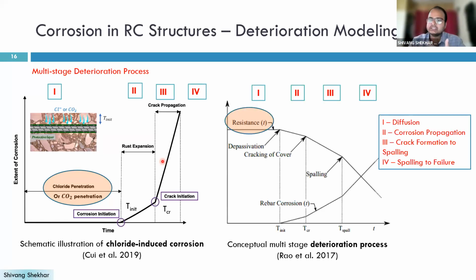In terms of resistance, you can see it here. Resistance is 100%, and once the corrosion starts, it starts to degrade, with cracking of concrete, then spalling of concrete. So basically we have 3 time instants: T initiation, the time to initiation of the corrosion; T critical, the time of cracking; and then the time of spalling of concrete. Your 4-stage multi-stage deterioration process is defined as diffusion of chloride or CO2 in the concrete, then corrosion propagation, crack formation, and cracking and spalling of the concrete.